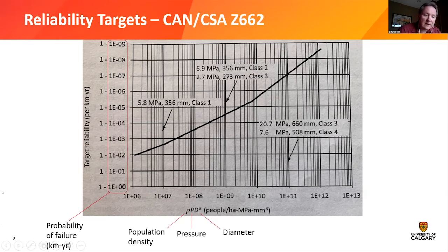And then we see here on the left the target reliability, which is 1 minus the probability of failure measured per kilometer and year. So we see smaller pipelines, they have a higher failure probability. And then as we get to larger pipelines in more populated areas, the failure probability needs to be reduced.